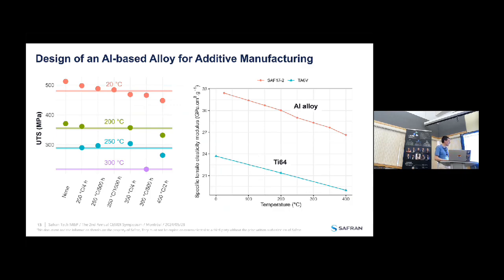Just to give you an idea of this alloy, it's quite a fun alloy. If you look at the tensile stress, the ultimate tensile stress, measured at different temperatures as a function of the heat treatment or the ageing temperature and time, you can see that if you look at the measurement at 20 degrees Celsius, even after 500 hours at 300 degrees, which is really hot for aluminum alloys, the material keeps its strength because of its precipitate strengthening. It's a very particular aluminum alloy with a lot of titanium. Everything is public. You can find it on the internet if you're interested. It's also a very high modulus alloy, with a specific modulus that is 20 to 25% higher than Ti64, even at 400 degrees.